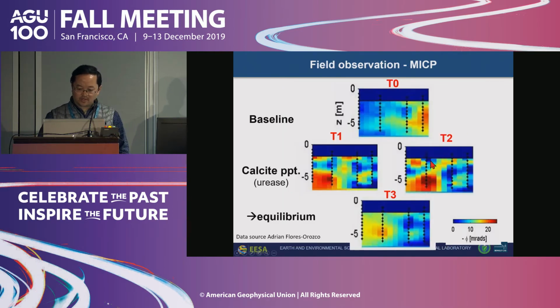This shows data from Rifle, Colorado, where you have the baseline condition, you have calcite precipitation in process, and you have this approaching equilibrium. You can see in this block the signal that is related to the calcite. But when the calcite precipitation stopped, the signal is disappearing. So this is a signal that you can observe in the field.